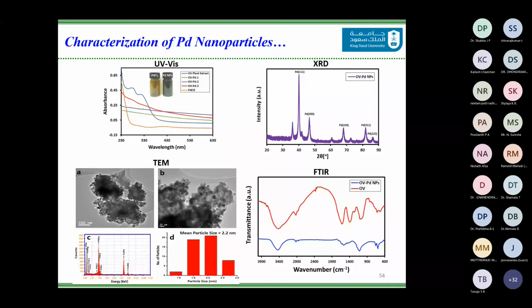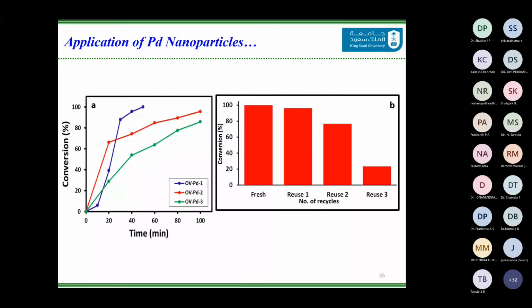And the stabilizing effect of the plant extract was confirmed by the FTIR spectrum, which showed the presence of plant extract on the surface of the nanoparticle, as well as the UV confirmed the reduction. We used various amounts of plant extract in this study to find out which nanoparticle obtained from plant extract will give us the best activity in the least time.